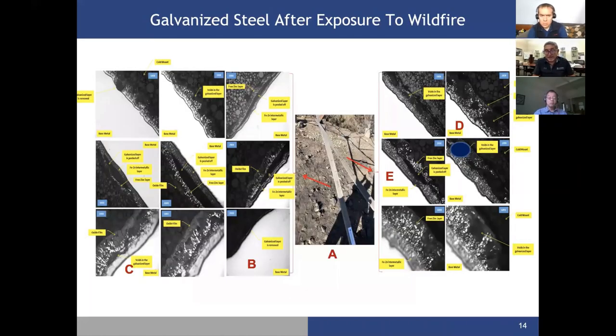Well, this slide is a more detailed study after doing the first indirect assessment; we call it direct assessment. Picture A shows that we looked at the structure that exhibits some type of serious problems as far as mechanical properties. And then we took a cross section, we polished it, we put it under a microscope, and let's go through these pictures together. Look at picture B. Literally, there is no galvanized layer on this surface anymore. That means this structure does not have any protection after exposure to wildfire.